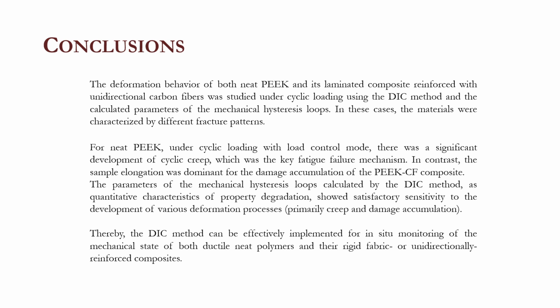Conclusions. The deformation behavior of both neat PEEK and its laminated composite reinforced with unidirectional carbon fibers was studied under cyclic loading using the DIC method and the calculated parameters of the mechanical hysteresis loops. In these cases, the materials were characterized by different fracture patterns. For neat PEEK, under cyclic loading with load control mode, there was a significant development of cyclic creep, which was the key fatigue failure mechanism.